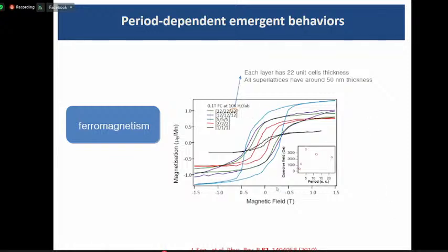Okay, let's see this one. They show very clear magnetic hysteresis. If we make 5 unit cell thickness of each layer, then it shows the largest hysteresis and magnetization. Then as the thickness gets thicker, the hysteresis becomes narrow, and the magnetization also becomes lower.